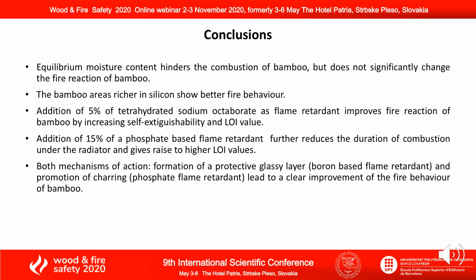Our conclusions are that the equilibrium moisture content hinders the combustion of bamboo, but does not significantly change the fire reaction of bamboo. The areas richer in silicon, especially the outside areas, show better fire behavior. The addition of 5% of boron-based flame retardant improved the fire reaction of bamboo by increasing self-extinguishability and limiting oxygen index value.